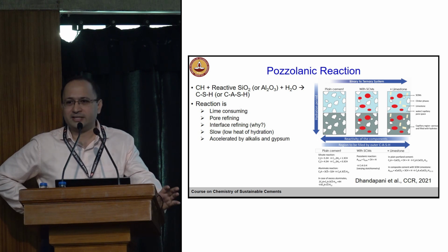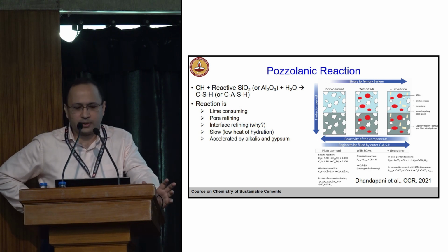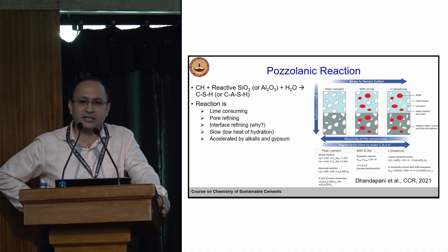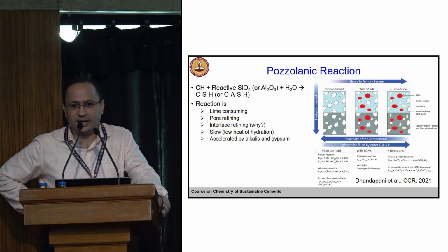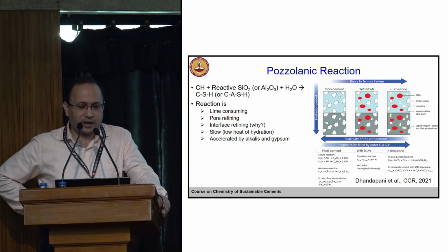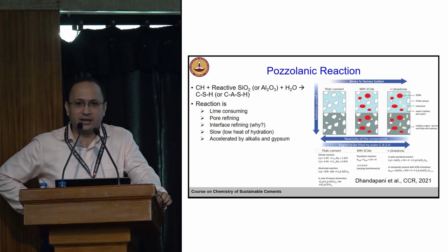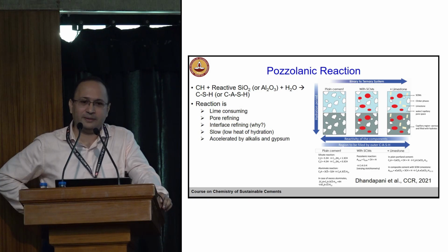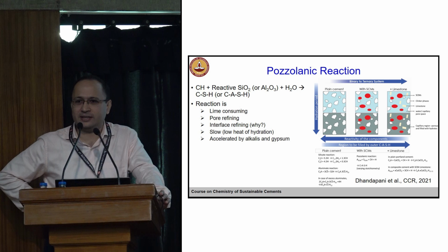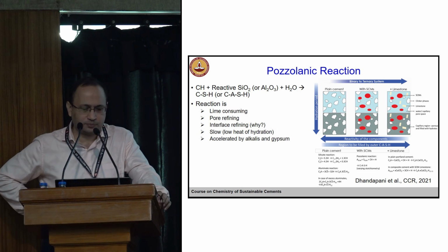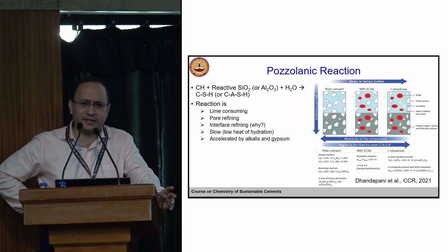So what is pozzolanic reaction? When this calcium hydroxide reacts with reactive silica or alumina to form additional CSH or calcium aluminosilicate hydrate. This is a very interesting reaction. It is lime consuming; we are consuming hydrated lime. It refines the pore structure. It refines the interface. But it's slow. Slow means low heat of hydration. It's not very fast, it takes some time. And it also gets affected by the alkalis and gypsum.